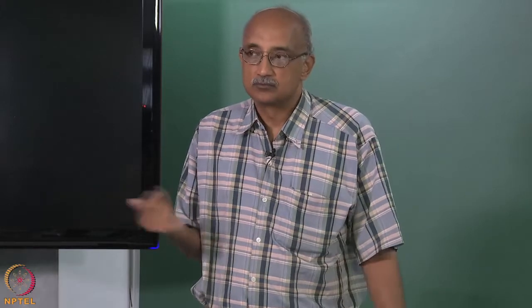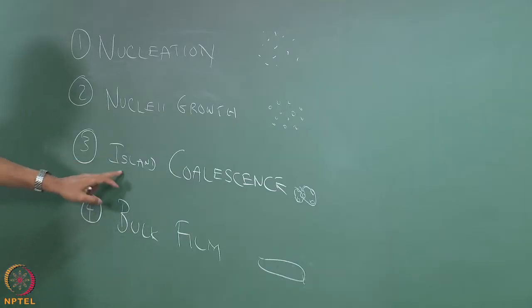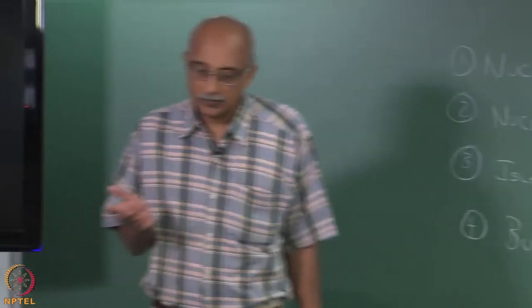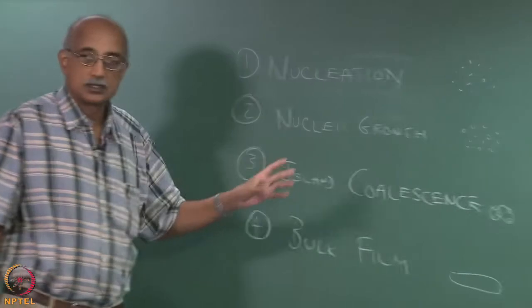If you have an extremely low energy surface, for example, if you try to do CVD on Teflon, it is very difficult to make it happen, unless you pre-energize the Teflon by bombarding it with plasma or ions or laser or something. But as it is, Teflon is an example of a very low surface energy surface which will not easily accommodate arriving vapor molecules. So surface energy, wettability of the surface. How easy is it to form a continuous film on the surface? Or is it going to keep breaking up? So even after you get past stage 3 and you're trying to get to stage 4, is this transition again thermodynamically favored? So there are a lot of issues that affect each of these steps in the process.